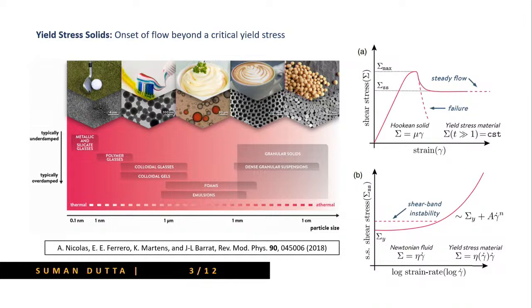And these are the typical behaviors that this class of materials shows. This is the typical load curve, the flow curve. If we go back to the earlier picture, initially when we are driving it with some stress and it is being deformed linearly, it behaves like a Hookean solid. This is the initial part, and then after some plastic events, they either fail, which happens in the case of a brittle failure. But these are yield stress materials, so the stress becomes constant here and they show a steady flow, and that separates them from other kinds of materials.